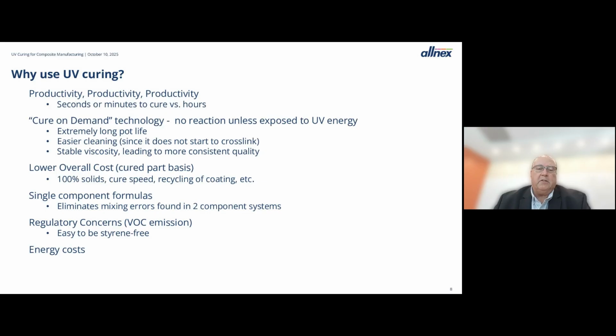This also means it's easier to clean equipment. As long as the UV material hasn't been exposed to UV light, it doesn't start to cross-link. So it's very easy to clean off the equipment, clean pipes, clean everything else. It also means there's a stable viscosity. With two component systems, once you mix them together, reaction does start taking place, and eventually your viscosity will start to build. With a UV system, the viscosity is fairly constant because it doesn't react until it's exposed to UV light. So productivity and cure on demand are probably the two big things.